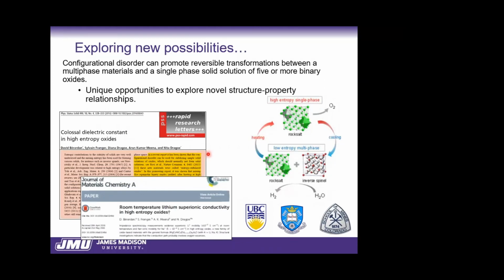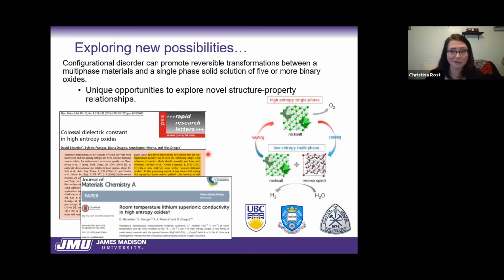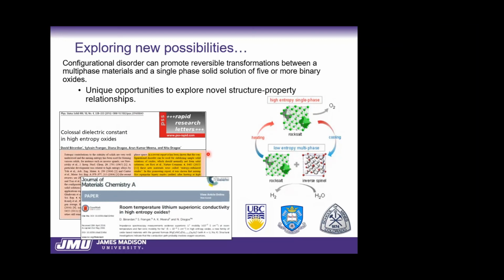Because it's sort of well known that for highly disordered systems, and these might be, a third cumulant can be important, and not including it often skews towards lower distances. Interesting. So it's worth looking into. Yes, absolutely. Thank you. Thanks.